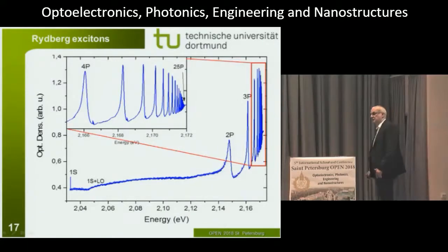I have to give credit to our Russian colleagues from St. Petersburg. They wanted to make an exhibition to honor Gross for the discovery of the exciton, and they approached us with all your fancy lasers: could you study the exciton series in these days and see where you end up? So what we do is we record the absorption by scanning the laser from lower energies to higher energies. We indeed can observe with these lasers the 1s exciton.